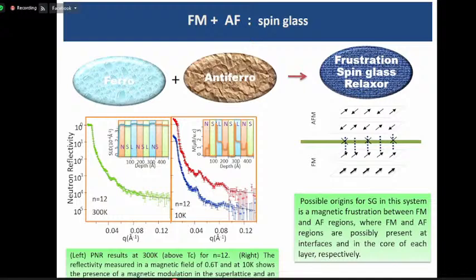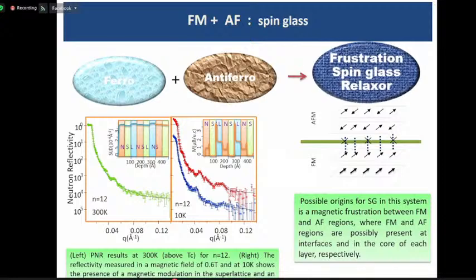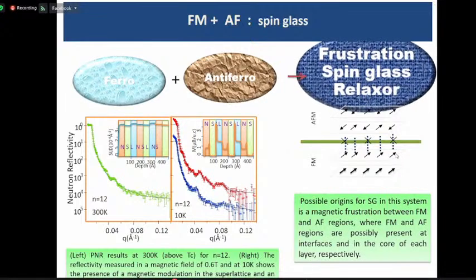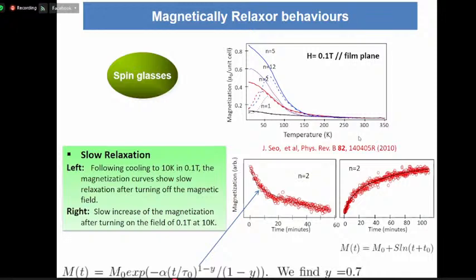Okay, then let's see. We said at the interface there is ferromagnetism, and far from the interface they have antiferromagnetism. If they are nearby each other, then what happens? Like this, the spin has some frustrations. So at the interface, the spin feels frustration, and that gives rise to some spin glasses. We found spin glass behavior as well.